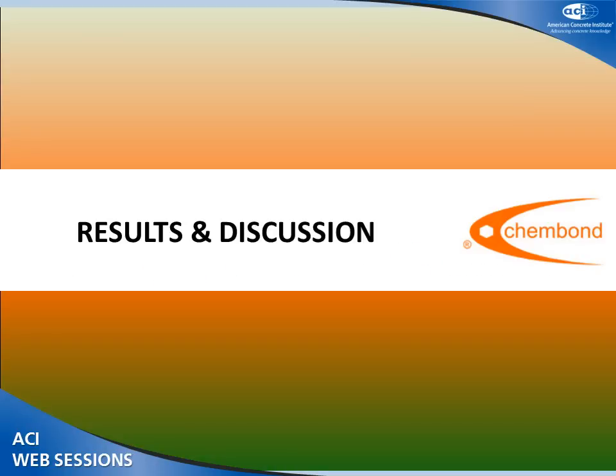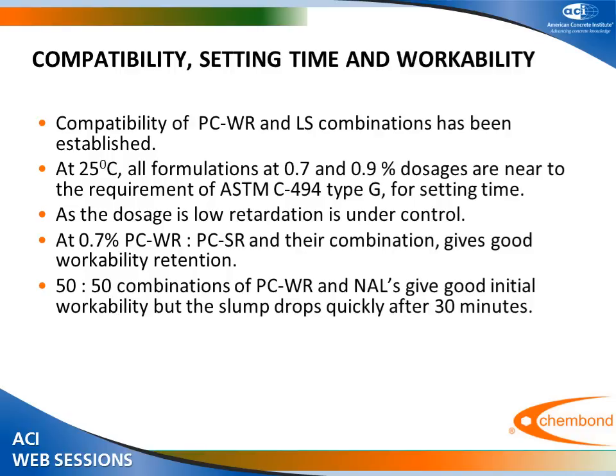So results and discussions. We have established the compatibility of PCWR and LS combinations in all the combinations that we have done. At 25 degrees centigrade, both 0.7 and 0.9% dosages are very near to the requirement of ASTM C494 type G setting times. As the dosage is low, retardation is under control, and 0.7% PCWR and PCSR and their combinations have given good workability retention.